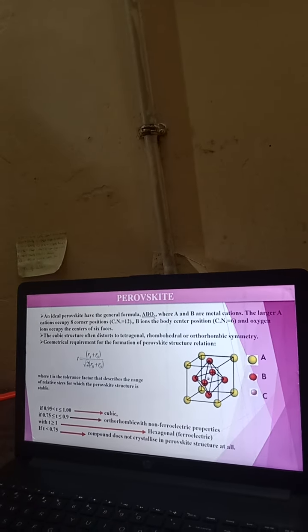The structure of the crystal is generally determined by a factor which is known as the tolerance factor. The formula of tolerance factor is t equals (Ra + Ro) upon root 2 times (Rb + Ro), where t is the tolerance factor and that describes the range of relative size for which the perovskite structure is stable. If t is between 0.95 to 1, then the structure of the crystal will be cubic.